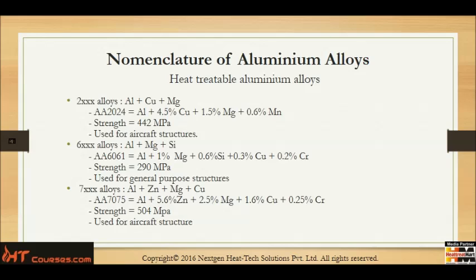6XXX is aluminum plus magnesium plus silicon, and that would embrace specifications such as 6061, which is aluminum plus 1% magnesium plus 0.6% silicon plus 0.3% copper plus 0.2% chrome. The tensile strength now increases to approximately 290 megapascals, and it's used for general purpose structures.